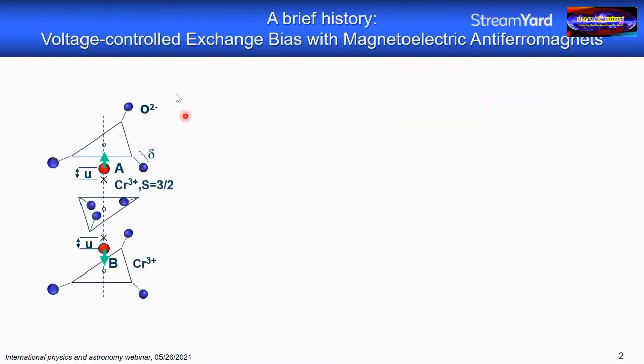So let me get started with a brief introduction on voltage-controlled exchange bias with magnetoelectric antiferromagnets. And even one step before, let me give a brief introduction, and everyone who is interested in the physics of magnetoelectrics may enjoy this: a very brief introduction to the magnetoelectric effect in this particular material, Cr2O3, chromia. Here you see a fraction of the unit cell of this material. This is the easy axis or c axis of the material. It's a threefold rotational symmetry axis. And here you see the chromium 3+ spins in red. The full magnetic unit cell has 4 of them. I show you here just 2 for simplicity, down and up orientation of the spin.